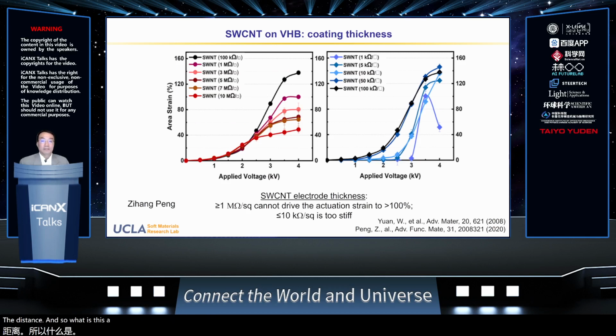What this experiment shows is that when the CNT layer is too thick, it's too stiff, and it prevents the actuation strain. When it's too thin, the electrode cannot drive larger strain actuation. Basically, the carbon nanotube network will lose continuity at high strains. So the sweet spot is when the sheet resistance is around 100 kilo ohm per square, like the dark data points in the left chart. At this kind of carbon nanotube coating thickness, the actuation strain could well exceed 100% in area expansion.